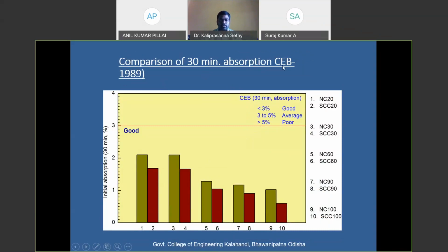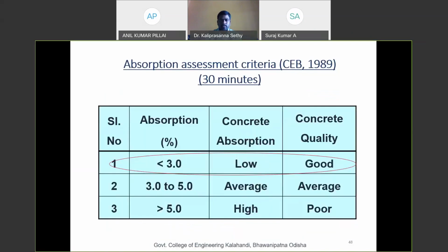And as per the Concrete Society standard, if the 30-minute absorption falls within 3%, the concretes are categorized as good concrete. So you can see all the concretes are under that limitation. So all the concretes are showing very good absorption value. So here is the limitation.